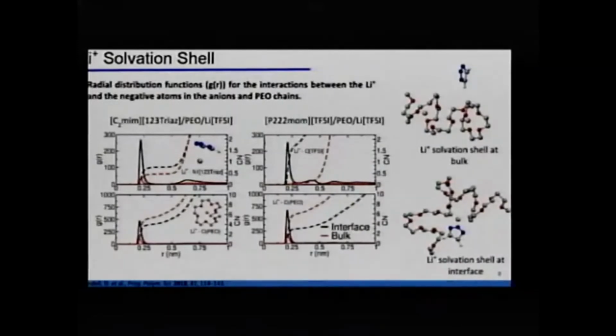The first row is the interaction between lithium and the anions, so lithium and triazolide, lithium and TFSI, and the second row is lithium and the ether oxygens in PEO. If we look here, in black is the interface region, and in red, the bulk region. Going from bulk to the interface, we see an increase in the coordination numbers of the anions around the lithium. That makes sense, because if we have a higher density of anions close to the interface, we have more